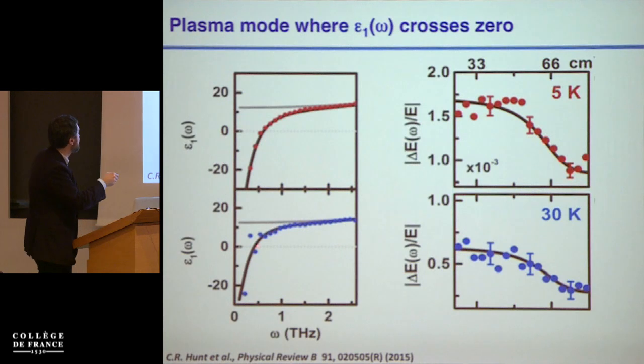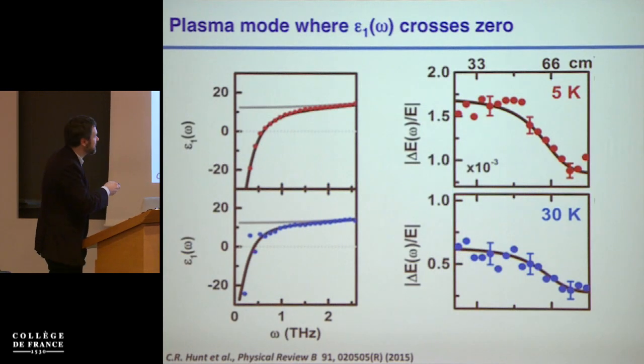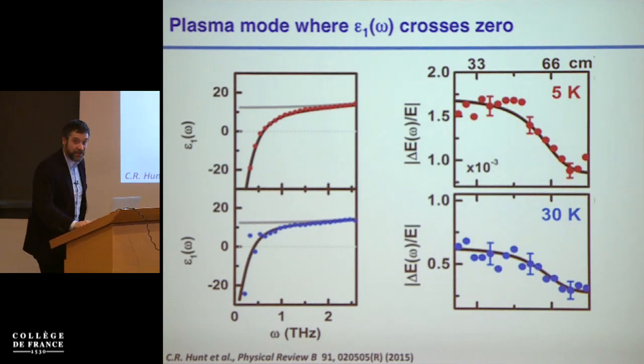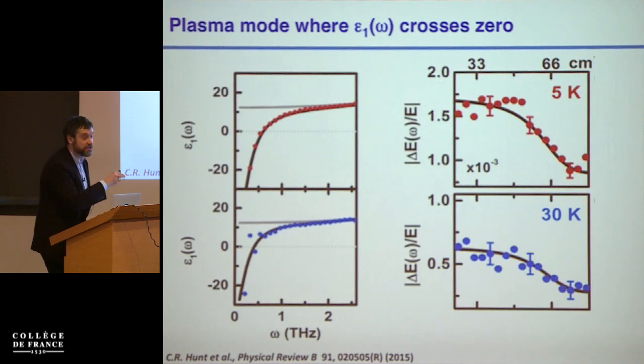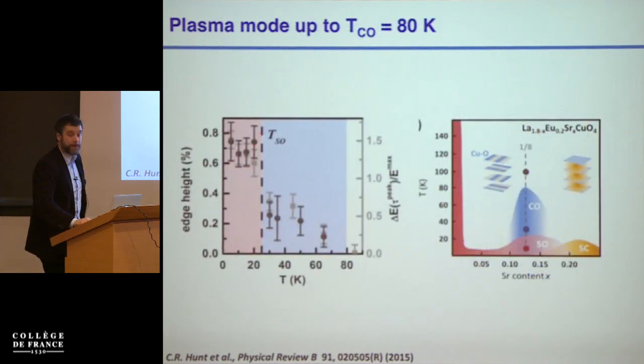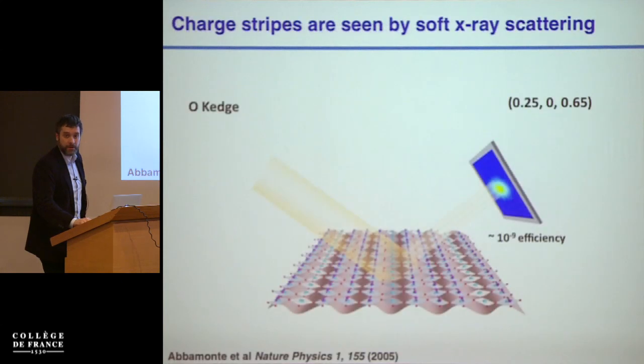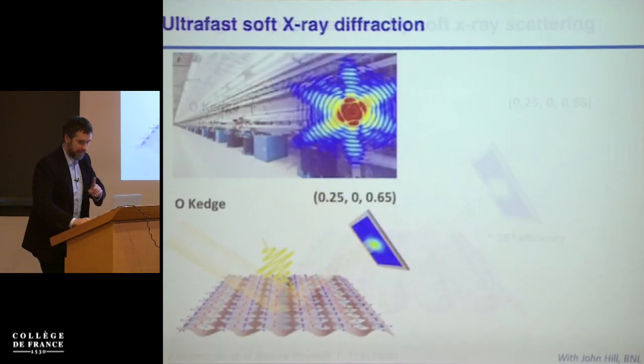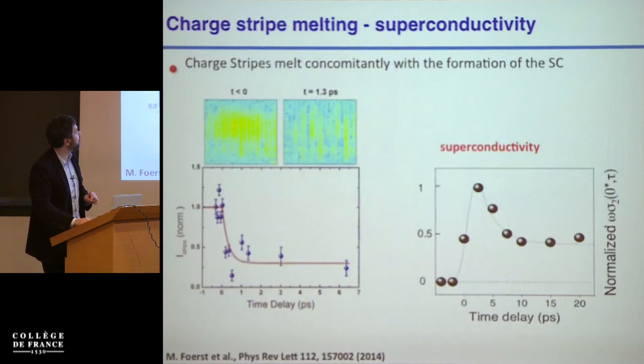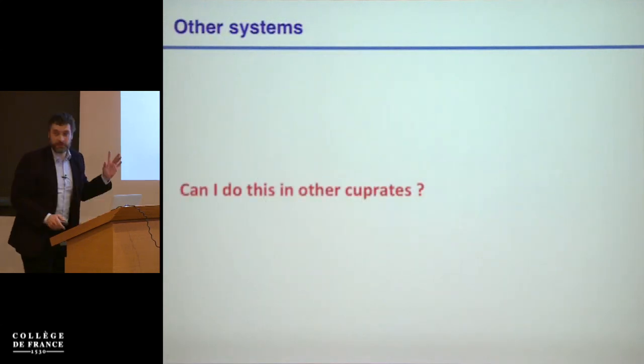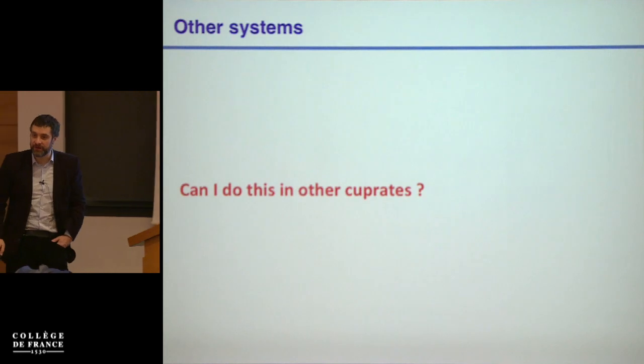And you can see this, epsilon 1 consistently crosses zero at temperatures higher than, okay, this is 30 Kelvin, so this is consistent with the 38 Kelvin of LSCO. Yes? For YBCO, you can go to T star. I'm getting there. So the next question is, can I do this in other cuprates? So I'm getting to YBCO. Yes? More or less the same.